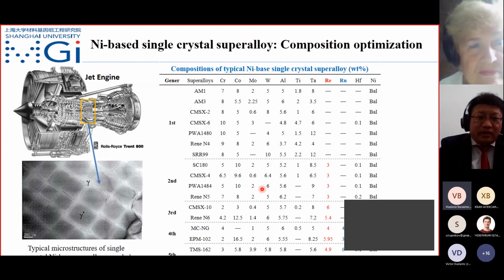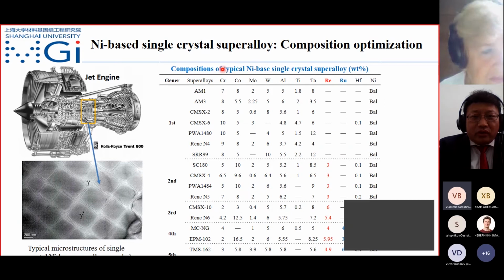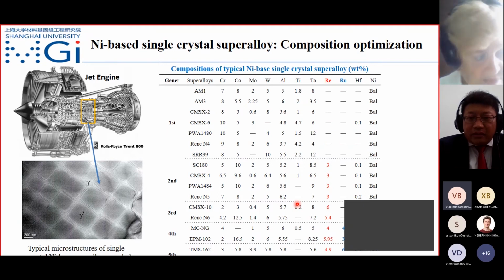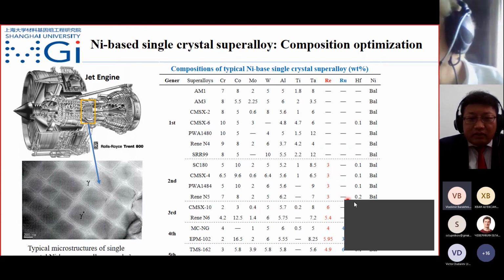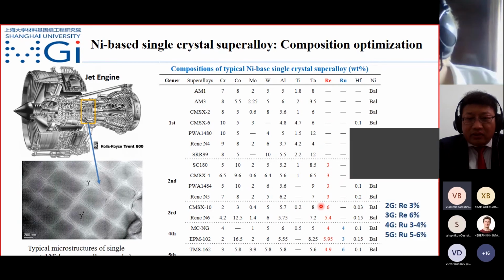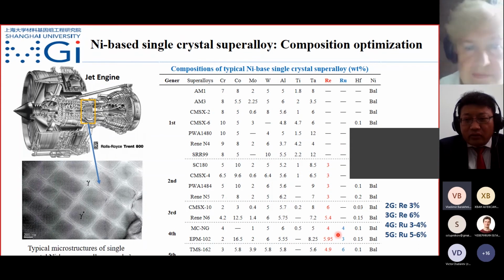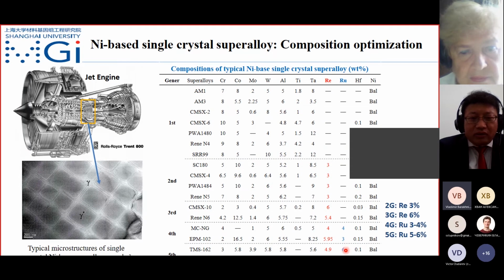In the example today, we are interested in developing superalloy, which is a turbine material used in jet engines. This is the traditional nickel-based single crystal superalloy. The composition looks very complex. It has more than 10 elements, and it evolves from the first generation up to the second, third, even fifth. The key difference between each generation is the element addition. For example, starting from the second generation we add rhenium, Re, and we add more Re at the third generation, and start to add ruthenium, Ru, from the fourth generation, and add more from the fifth generation.